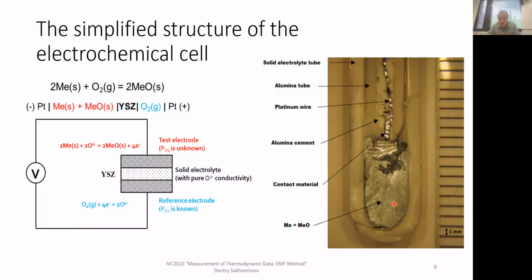Another rather common option is air. The concentration of oxygen in air is also fixed at 0.21, it doesn't change. Quite a good option as well, and it's easily available. And then our test electrode. Here we have a generalized, simple example: a metal and its corresponding oxide. And then the reaction happening at the test electrode compartment: 2 moles of metal plus 2 moles of oxygen ions equal 2 moles of metal oxide and 4 electrons. Then we also have the reaction happening on the reference electrode, in case it is gaseous.